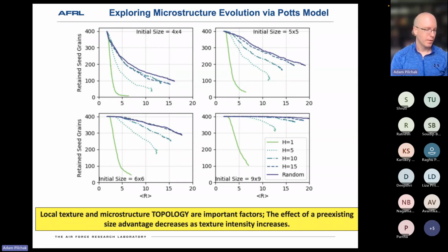So ultimately, what these simulations showed is that there is a kind of complex interplay between the size advantage and the neighbors. Initially we thought just the first nearest neighbors were going to be controlling this behavior, but ultimately it ended up being the second and third shells, and their influence on that first nearest neighbor shell and its influence on the seed grain, that ended up being really important. So there's still more to unravel here. So this is kind of ripe for additional work.